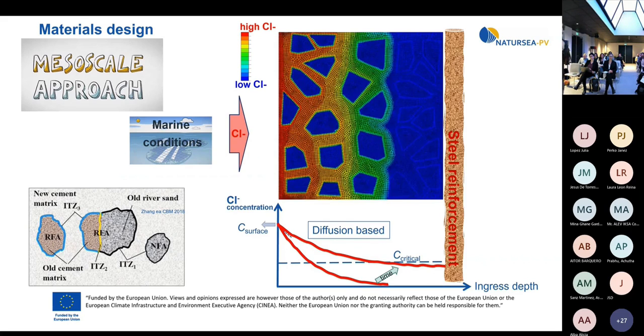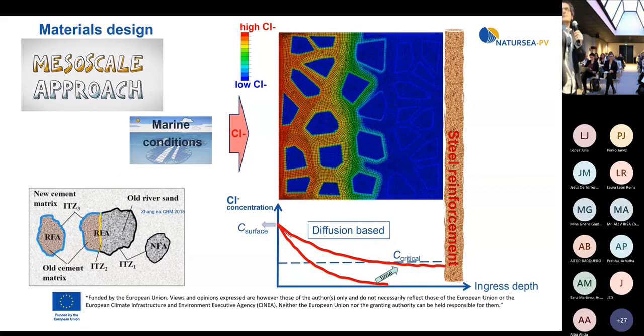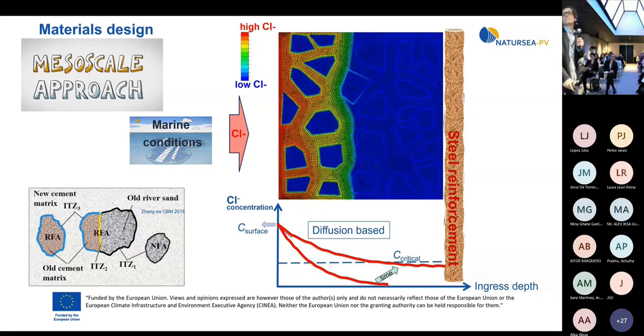In the mesoscale approach you can see here a simulation of how the chloride is ingressing, and those are the aggregates. Here we have the steel bar, and here we have the chloride profile, and there is a certain critical concentration. When this critical concentration is reached at the rebar level, the reinforcement steel, corrosion starts. This is what we don't want. If this is reached, then you need to remove the concrete cover and put a new one.